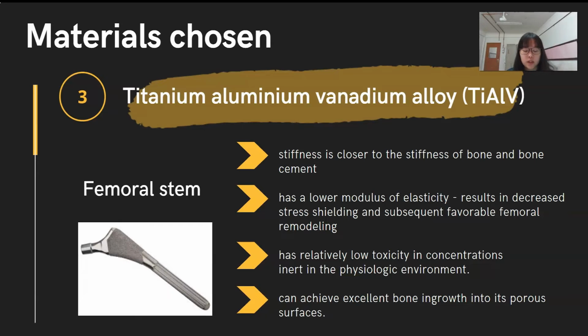This is because its stiffness is closer to the stiffness of bone and the bone cement. This material has a lower modulus of elasticity, which results in decreased stress shielding and subsequent favorable femoral remodeling. Titanium aluminum vanadium alloy is of relatively low toxicity in the concentrations found clinically, and this material is inert in the physiologic environment. Besides, titanium aluminum vanadium alloy can achieve excellent bone ingrowth into its porous surface.